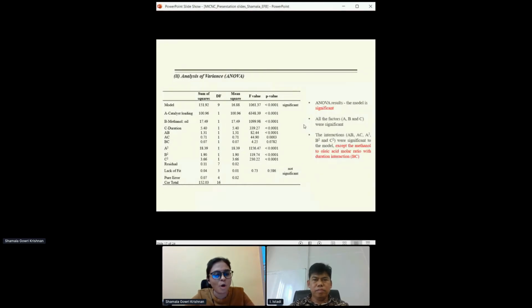Based on the optimization results, analysis of variance, or ANOVA in short, was conducted, and it was observed that the model is significant as the p-value is less than 0.05. Besides, all the primary factors were also significant along with the interaction factors AB, AC, and A square, B square, and C square, except the methanol to oleic acid molar ratio with duration interaction, which has a p-value of more than 0.05.